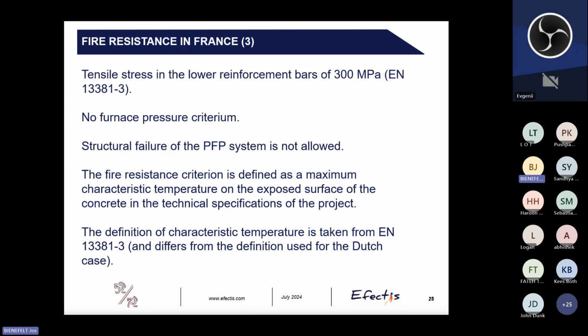Worth mentioning is that for these tests, a tensile stress in the low reinforcement bars is induced. So that differs from the Dutch case, which we see later, wherein a compressive stress is induced at the heated side. Compressive stresses usually have a negative influence on the spalling behavior of concrete. So no furnace pressure criterion in this case, and structural failure of the PFP system is not allowed.